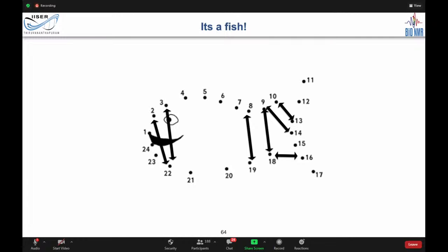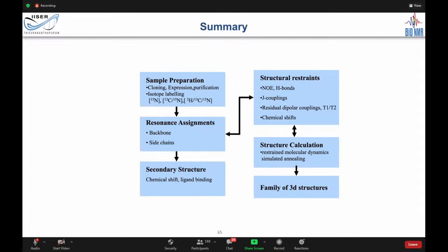And of course, one does the structure calculation using molecular dynamics simulation, using a simulated annealing protocol, where we heat the molecule to a very high temperature and then cool it by adding restraints: NOEs, J coupling, residual dipolar coupling, chemical shifts, all of that. Then we get a bunch of structures which satisfy all our experimental data, and that is what the model of a molecule would be.